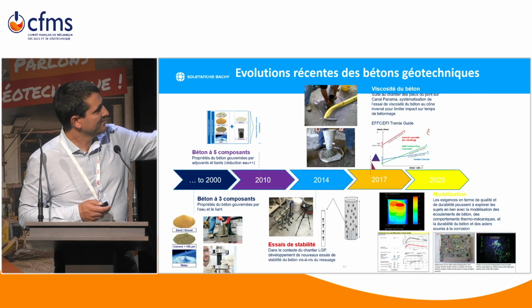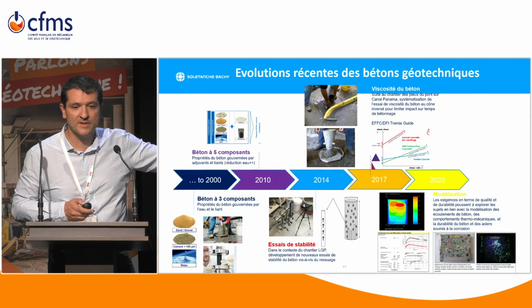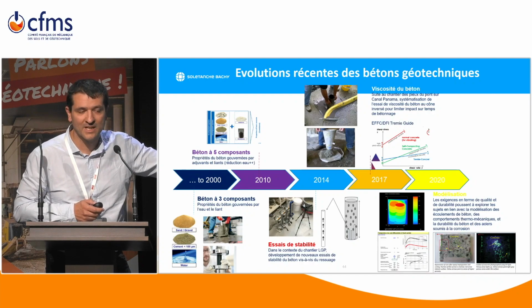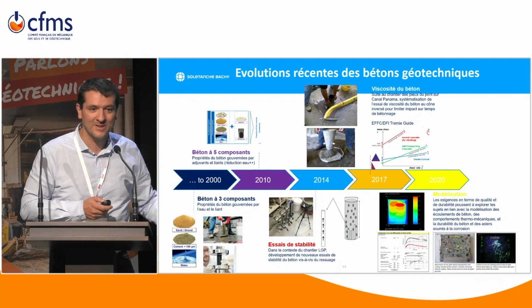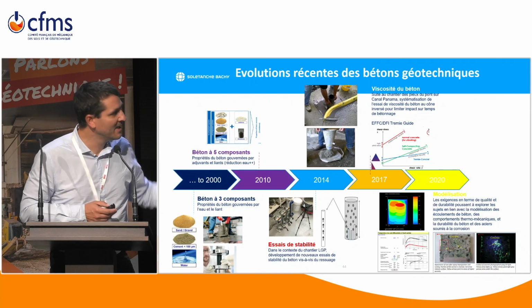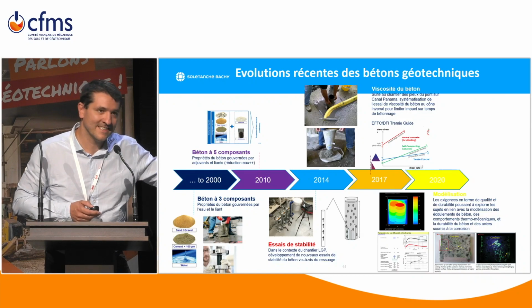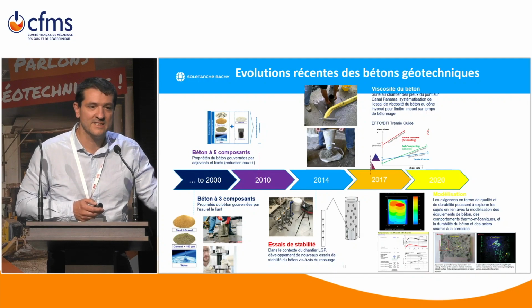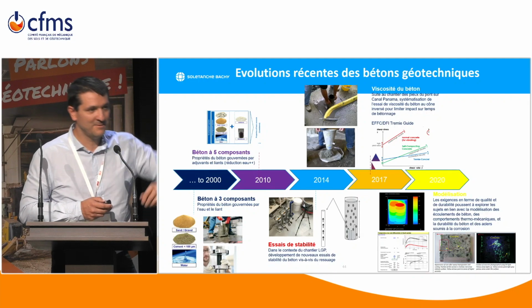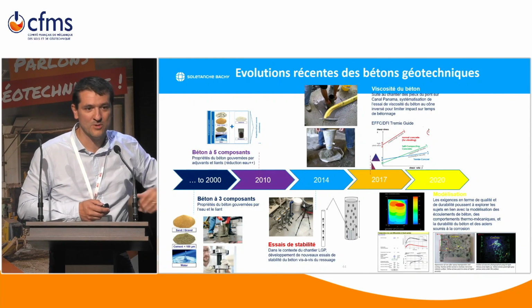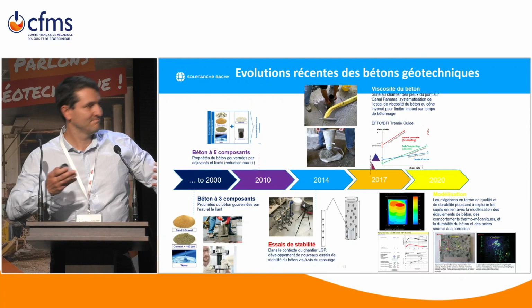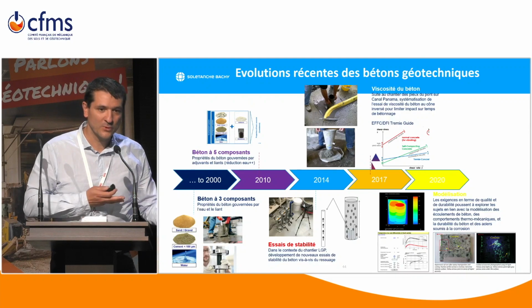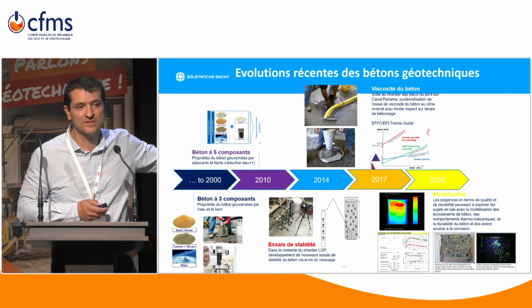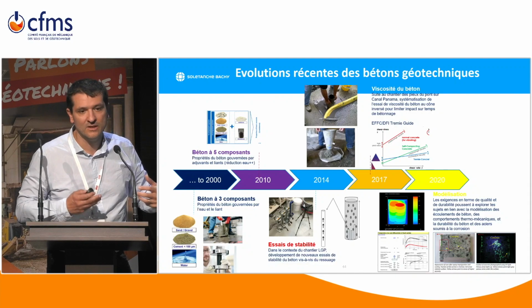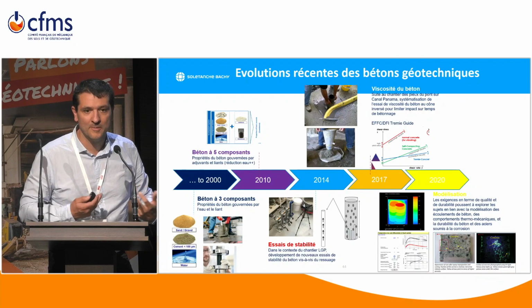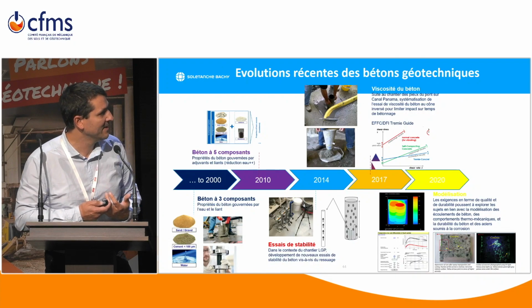So just imagine, when I arrived in 2005, the only thing we were doing in concrete for D-walls and piles was a slump and cylinders to test the compressive strength. Now in France, most of the contractors are using at least 5 different tests on concrete. If you go to the UK or other countries, sometimes you have a list of 10 tests. I'm not saying that 10 is too much, but the 4 or 5 that we have retained and put into standard in France are really a change and help to increase the quality of the concrete we are building.